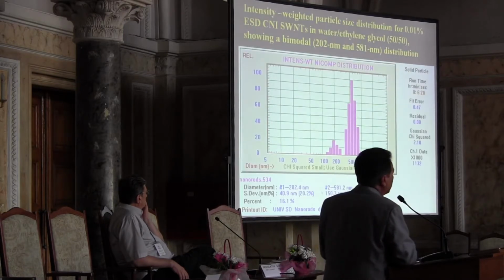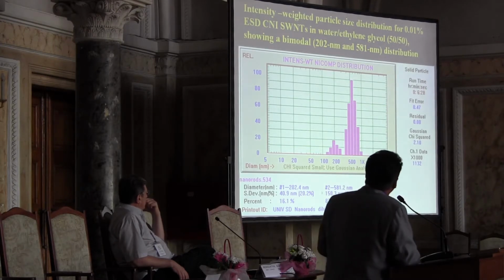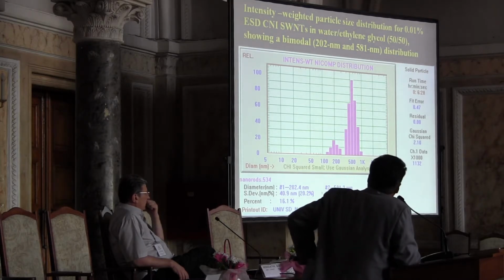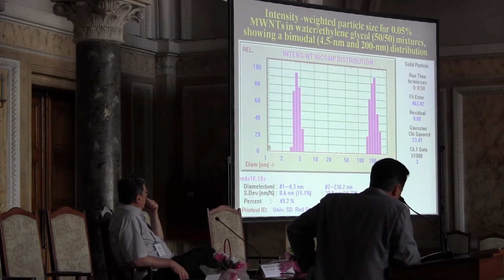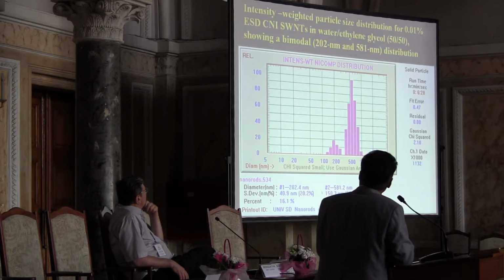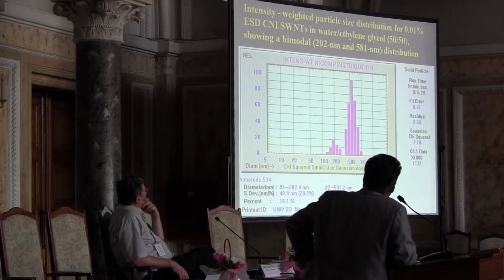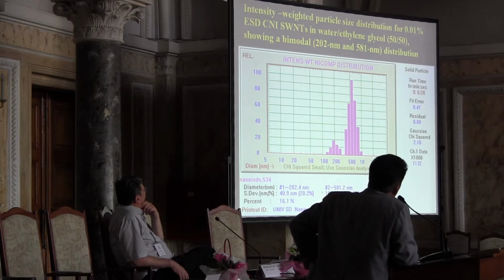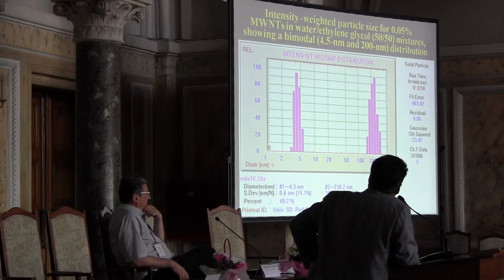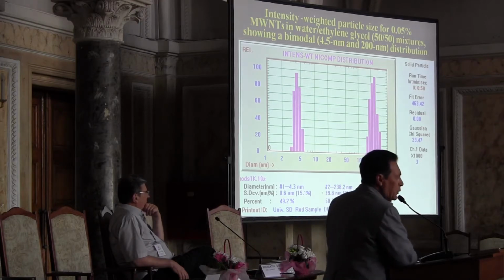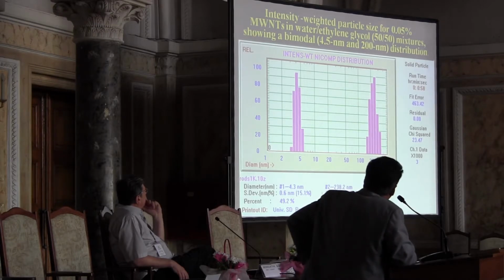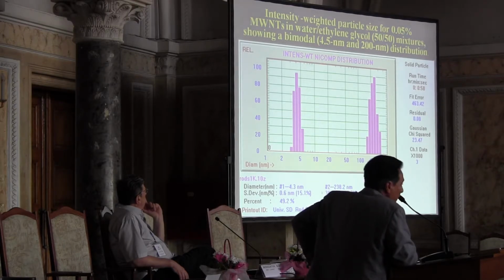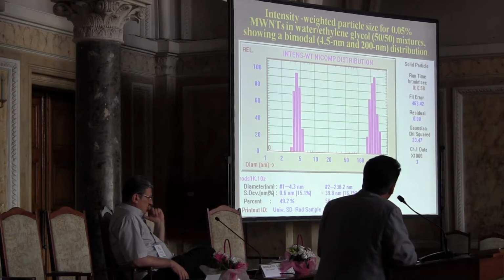And if you are measuring what you have in the fluid, that depends very much on whether you are dealing with single walls or multi-walls. In this particular case, you have the single walls in here. And so you are talking about the modal distribution when you have 200, 600, okay? But if you are dealing with the multi-walls, because you can disperse them better, that modal distribution is of the order of 4.5, okay, 200, okay? And this is what you are obtaining really in the experiment.